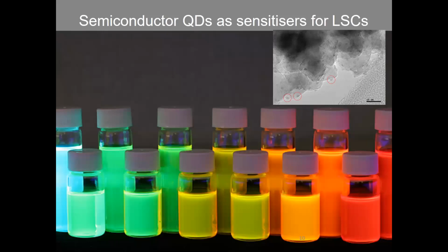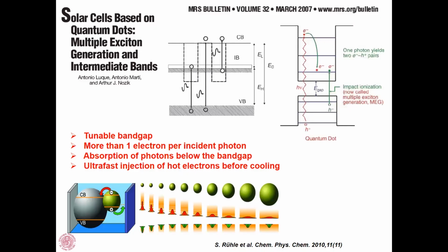Semiconducting nanocrystals allow you to change the energy gap of your crystals, so the absorption and the emission, just by tuning the size, and that's the first step. But then you can tune the electronic properties of these materials by playing with their structure in a core shell geometry. They have been proposed for photovoltaic applications in solar cells due to intraband transitions and multiple exciton generation. But here we're not interested in these features, but rather in two main features of these crystals: the high quantum yield, so the possibility to re-emit as much as possible of the absorbed radiation, and the large Stokes shift. Of course, the Stokes shift means a loss of energy, but the energy lost in this case is almost negligible.